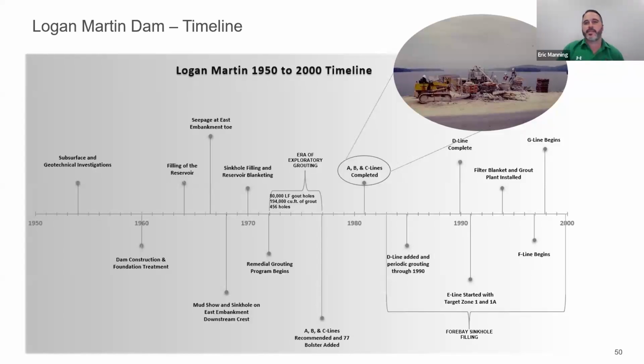At that stage in the program, deep leakage wasn't of a lot of concern, because it wasn't considered a risk to the dike's stability. So for that reason, A through C lines were only grouted down to roughly about 100 feet into rock.